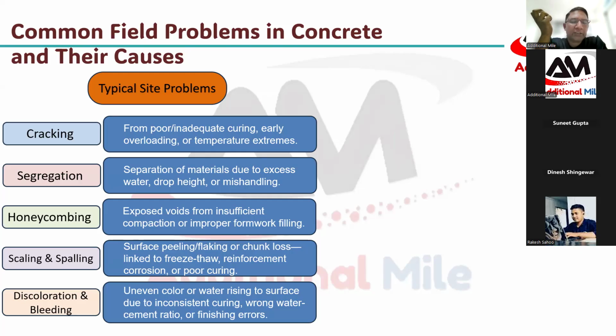Honeycombing, obviously, as I mentioned, is due to low vibration or improper formwork filling. There may be gaps in the formwork, as most of the time we reuse the form plates or formwork sheets. We always forget to plug the tie rod holes, which will allow the slurry to go out, and honeycomb happens. Sometimes excessive vibration: slurry goes to one side, aggregate sits on one side.